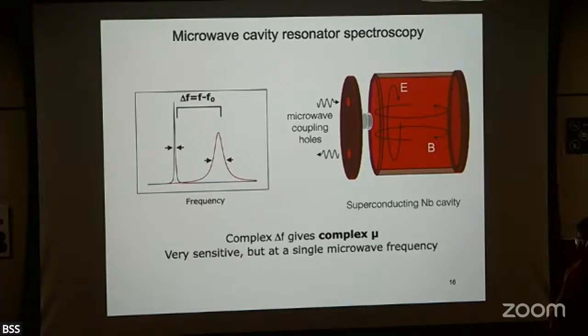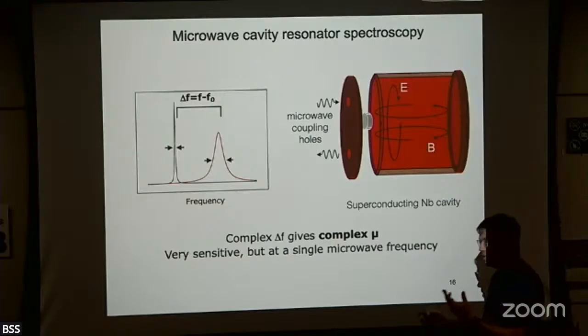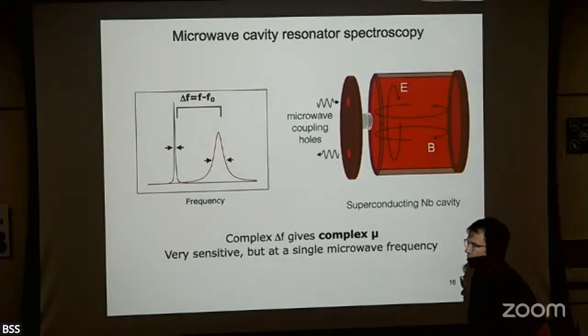The shift doesn't depend on the geometry of the matter, only on the volume, in the perturbation. It does depend on its shape. That's right. It's classical electrodynamics, and so you would imagine there's a kind of a depolarization factor inside. Some approximations typically have to be made. The simplest thing that you could solve basically exactly would be an infinitesimally small ellipsoid placed in a region of field extrema inside the cavity. We're never in that limit, but some people like to use needles or discs because we can approximate those as ellipsoids.